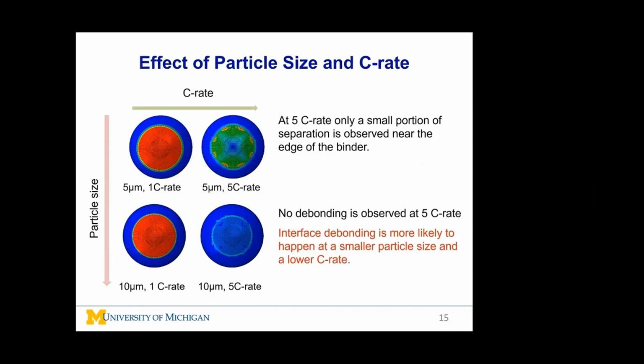Interestingly, we find that interface debonding is more likely to happen at a smaller particle size and a lower C rate, which is opposite to the case of fracture inside a particle. So we have a window of particle size, not too large to avoid crack in the particle, and not too small to avoid delamination from the binder.